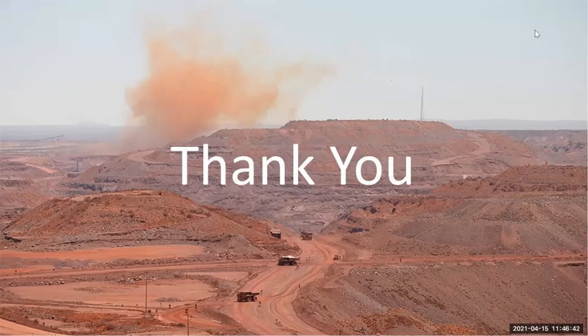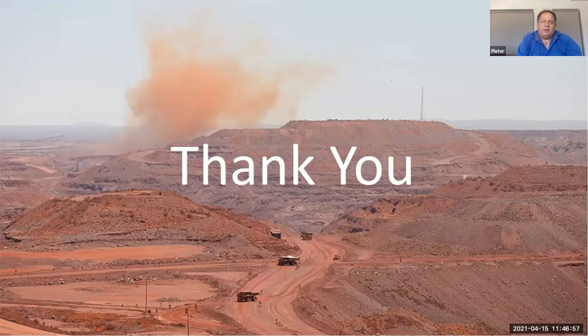It was just the influence it would have if you do blending of that stockpile with low and high grades. So definitely the variability in a stockpile is critical to understand when you want to do blending, and how you can make sure that material gets homogeneous to your plant. What we've done at our operations is we reclaim the stockpiles and we build finger rows. Then we reclaim the stockpile from the sides to minimize the variability, which gives you a better constant feed into the plant for blending purposes.